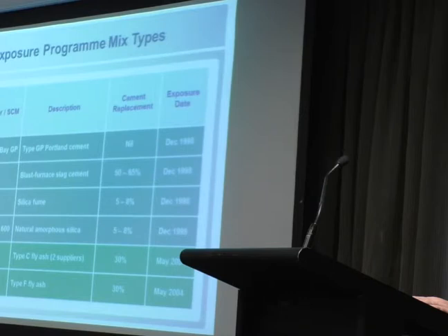So that's just a list of some of the concrete mixes that were included. So initially there were four types of concrete: standard Portland cement as required by the code, blast furnace slag cement, silica fume, and a natural amorphous silica that was locally mined in New Zealand. And later, three types of fly ash were also added to the exposure site programs.